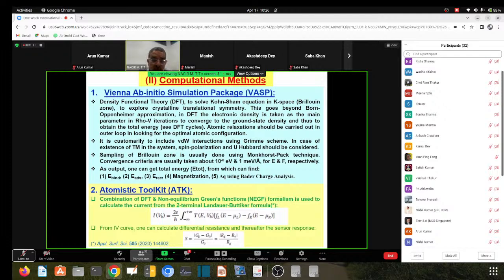And I believe most of the attendees have that experience. It is customary to include van der Waals interactions using the Grimme scheme in case of existing transition metal structures. In case of transition metal atoms in the system, we have to use spin polarization, and the Hubbard U should be considered. Sampling of the Brillouin zone is usually done using the Monkhorst-Pack technique. Convergence criteria are usually taken about 10 to the minus 6 electron volt for the energy and 1 milli-electron volt per angstrom for the force. As outputs, we use total energy to calculate the binding energy in case of metals embedded, or adsorption in case of molecules on the surface of the system, or desorption energy in case of, for example, hydrogen storage to look for the uptake capacity, or batteries also to look for uptake capacity of metals. We calculate also magnetization, and transferred charge using Bader charge analysis.